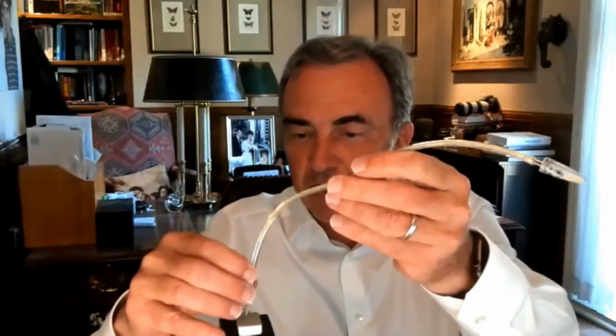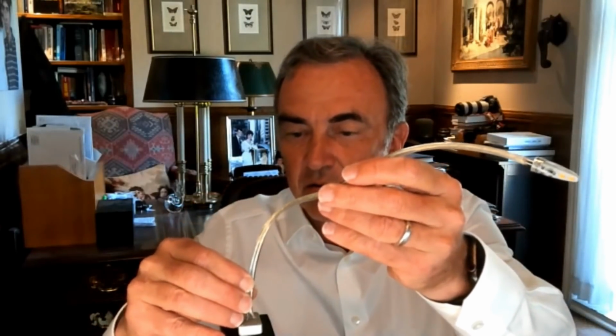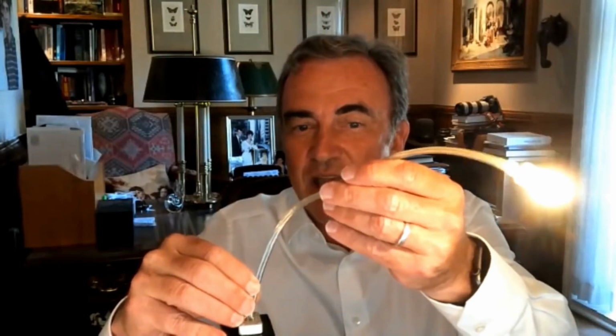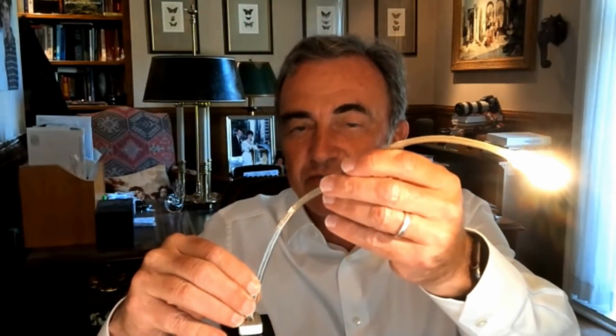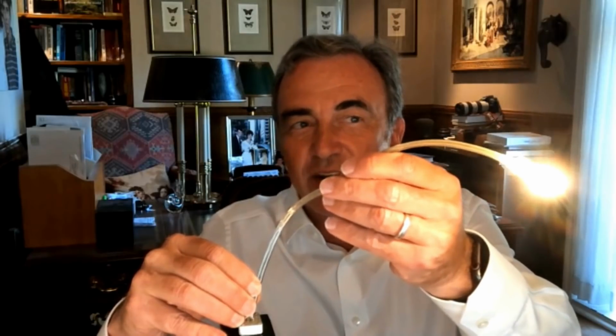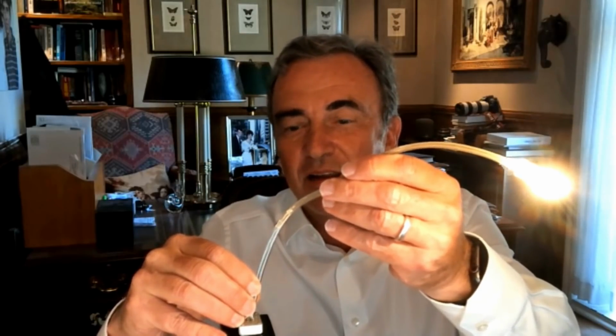Okay. And so what I'm doing is that I'm going to plug the nanowires into the graphite particle. Okay. You see what happened? The electrons flow from the graphite into the nanowires all the way to the tip. And if I move a little bit, it stops. So you can tell that the important point is that there is a connection here between the silicon and the graphite.